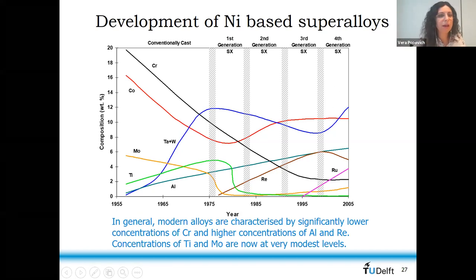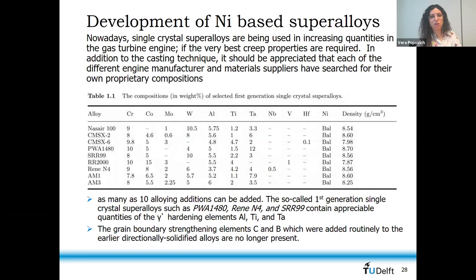fourth generation, and they all used, for example, rhenium. You see that they are increasing the amount of rhenium because they are good for high temperature properties. The concentration of chromium, for example, is going down, while the concentration of aluminium and rhenium is going up. So this is a kind of balance that you always have to address, but in general, what we see